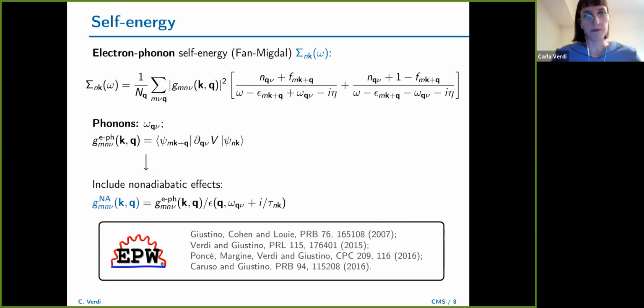Now, this whole self-energy, to calculate it is actually quite expensive. In particular, the electron-phonon matrix elements can be obtained by what is called density functional perturbation theory, but it is expensive. And what you need to be careful about is that these summations over bands and Brillouin zone momenta require up to a million points. And this is because of the very small energy scales involved and the rapidly fluctuating functions. So these calculations are performed using this code called EPW, which is part of the Quantum ESPRESSO distribution. And all the details are included in these references.